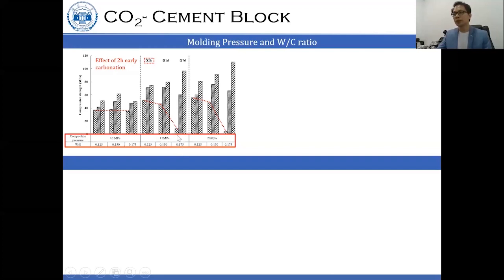At this situation, we could have liquid blocking the CO2 diffusion. However, if we further cure with water until 1 and 7 days, we see there is no significant difference for the different water to solid ratio. But as we increase the molding pressure and increase the water to solid ratio, we will in turn increase the compressive strength of the sample.